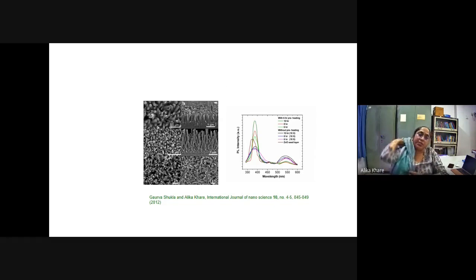Another application on ZnO itself was that after a little tuning of the conditions, we were able to grow ZnO nanorods, and we demonstrated frequency up-conversion with them.